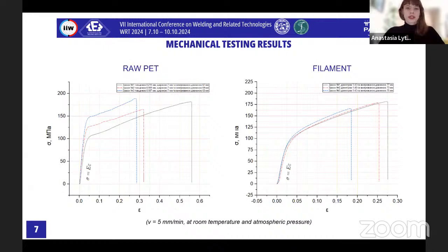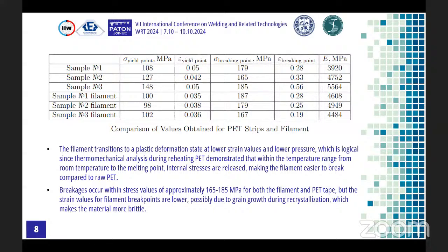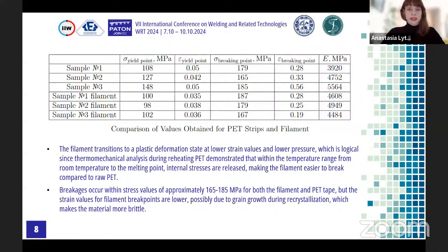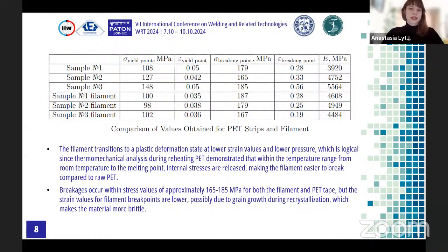It depends on the strength of atomic bonds. The crystalline structure influences how far these bonds can stretch, and therefore it can be asserted that after heating to melting temperature, which we did for the filament, molecules reorganize, leading to intermolecular strengthening, making the filament probably more resistant to deformation compared to the raw PET. So here's the results comparison. The filament transitions to a plastic deformation state at lower strain values and lower pressure, which is logical since thermomechanical analysis during reheating PET demonstrates that within the temperature range from room temperature, I'll show it later in the next experiment.